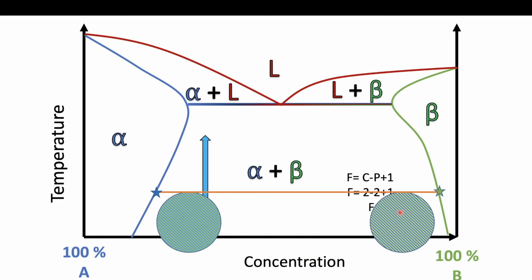That's the only thing that is concentration is changing, and it's not actually changing the composition of the phases itself. So now if you change the temperature, what happens is that the composition of alpha and beta will get automatically fixed depending on the temperature, and these points will lie along these boundaries. So in truth, as you also see, that what you are changing is one thing at a time. That is, you are changing only temperature and the compositions get fixed. And the change in concentration only results in a change in phase fraction, but not actual change in the composition of the phases. So this is in fact true that we have only 1 degree of freedom.